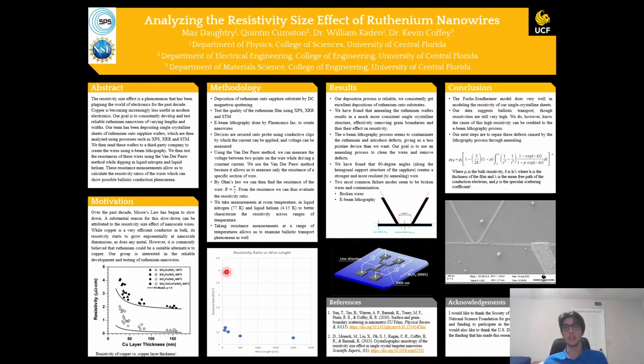It seems that the e-beam lithography process is where we're getting most of our contamination and defects in the ruthenium. So it seems that the e-beam lithography leaves a residue, or splotches of residue, just due to the inherent process of e-beam lithography, and maybe adds some defects to the ruthenium itself. Our goal is to use an annealing process to remove these defects and find a way to remove any of this contamination that we're getting.